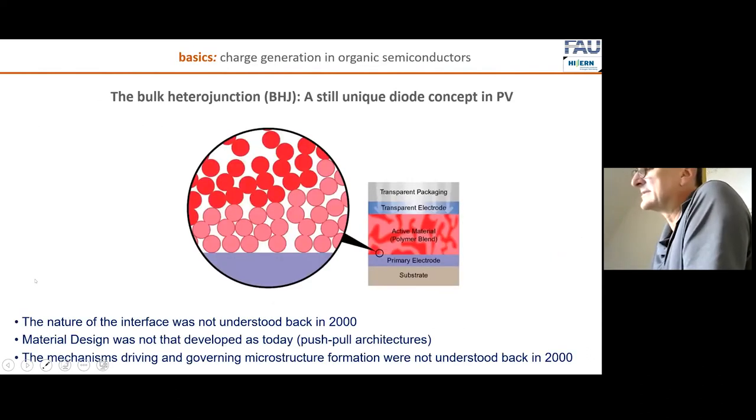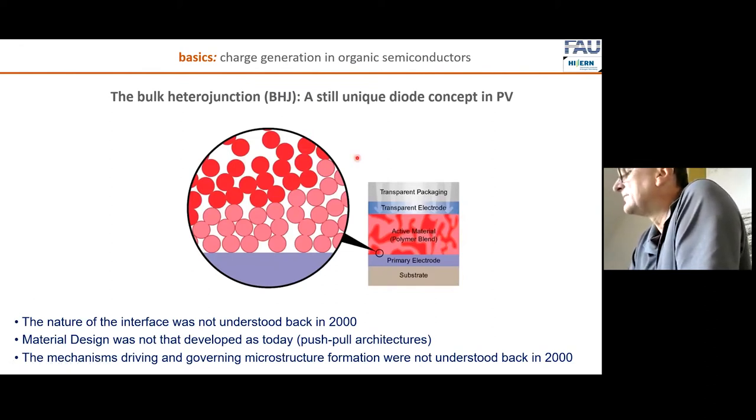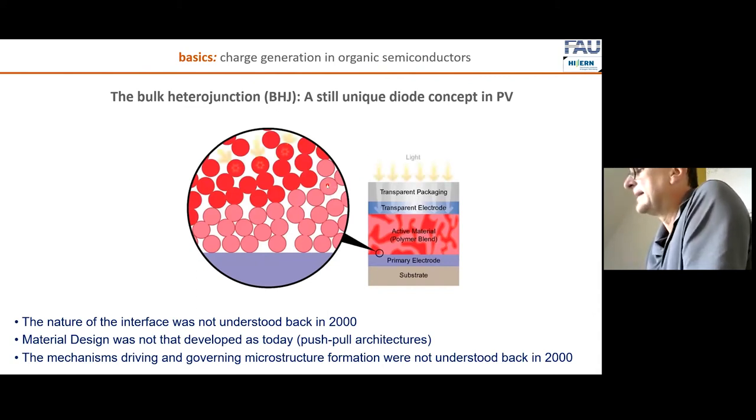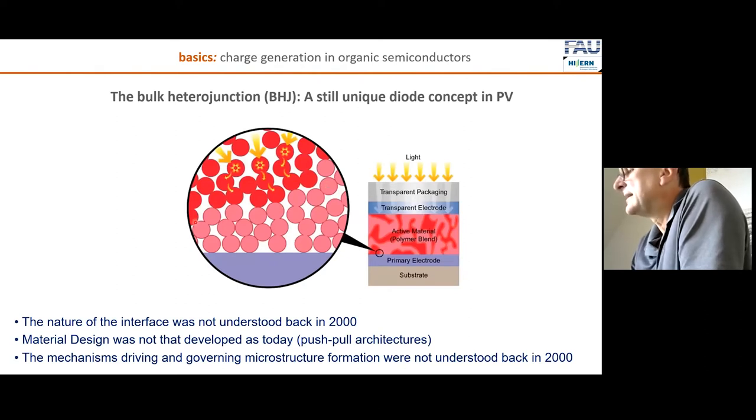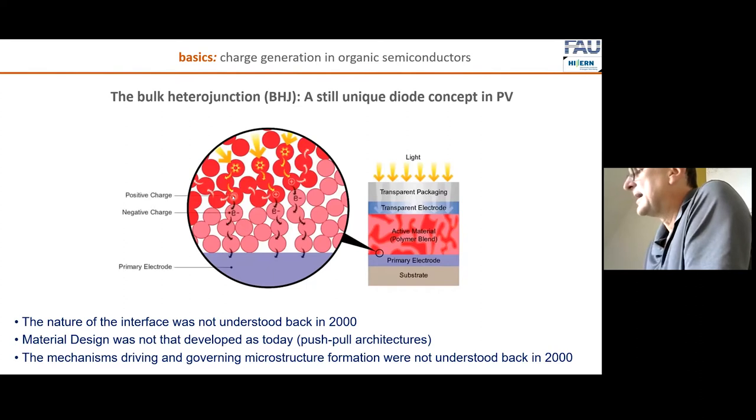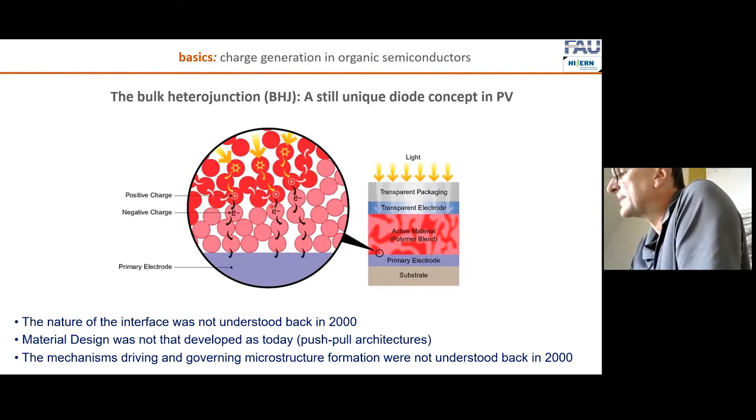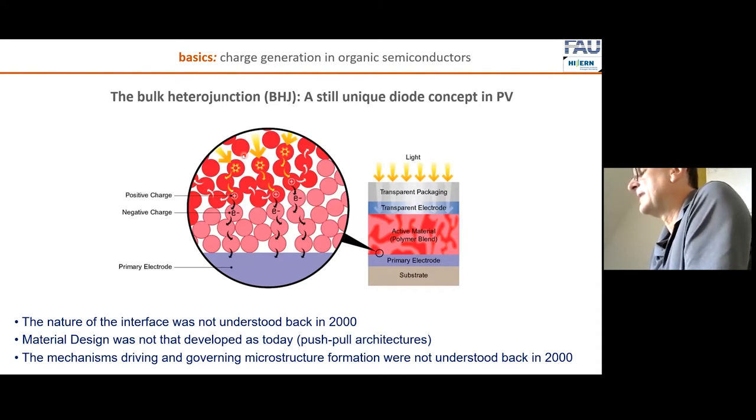Now, this we can regard as a molecular diode. A molecular diode is a great piece for a solar cell, but you have to imagine a solar cell is a macroscopic device. So this means you have to understand how to arrange and how to order and how to distribute this molecular diode in space. And that was, for quite a while, it was not understood that the most homogeneous mixing is actually a disadvantage, because the more you mix these two systems, the more you have recombination and losses. And only when you start to get a phase separation between the systems—and this was pioneered by Sean Shaheen almost 20 years ago—only if you get this phase separation, which you can see here also by the AFM images, then you create domains, and these domains may have a purity, and the purity and the size of the domains is actually determining the performance.